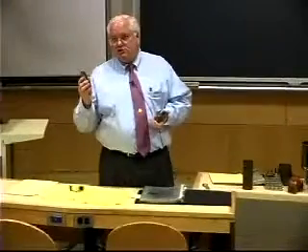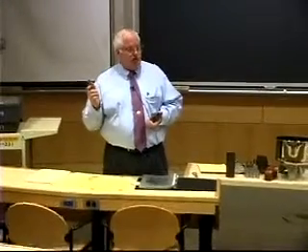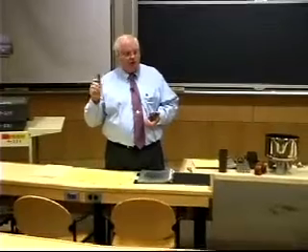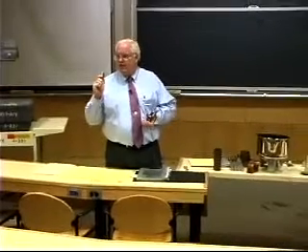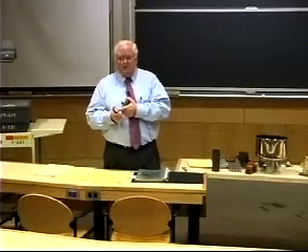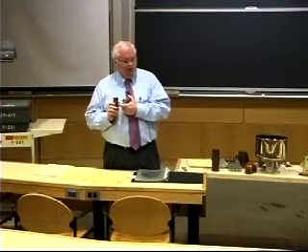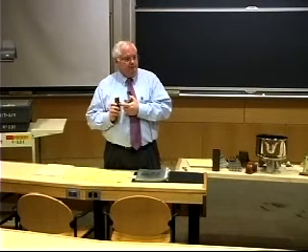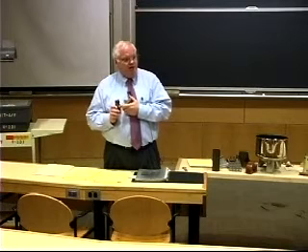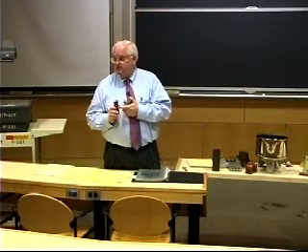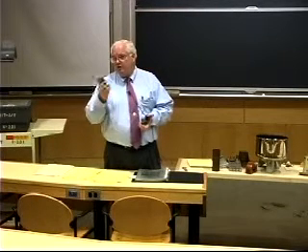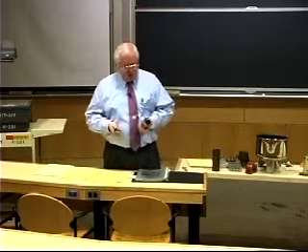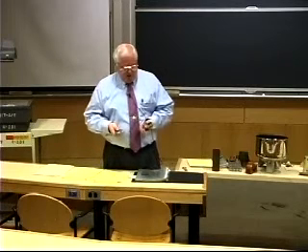What's the advantage of this? The defects are smaller. If the maximum flaw size is proportional to the casting size, each little casting is just a little bead here that's not much bigger than a ballpoint pen tip. So the flaw size should be very small in these things, and in fact it is. It also solidifies rapidly. You can get interesting microstructures and properties from something like this.